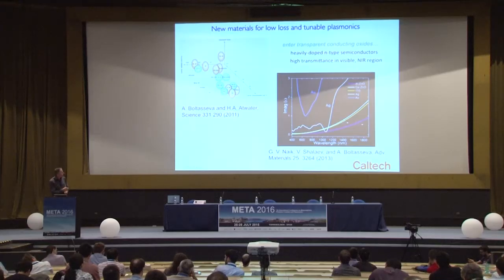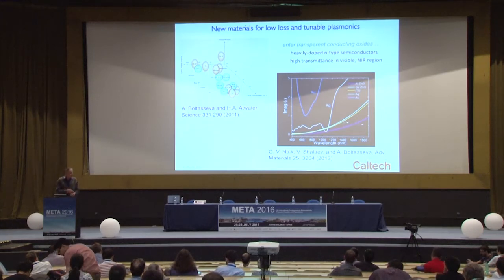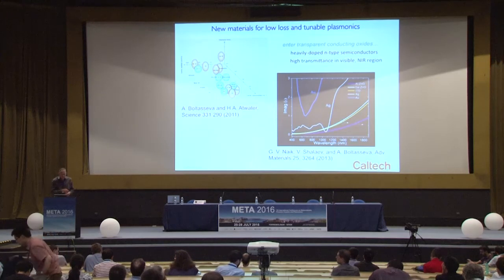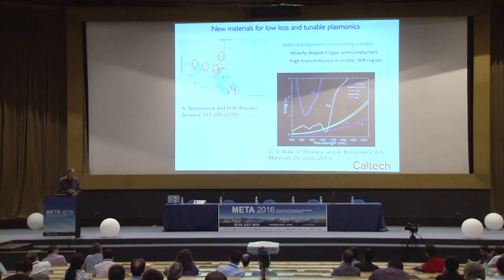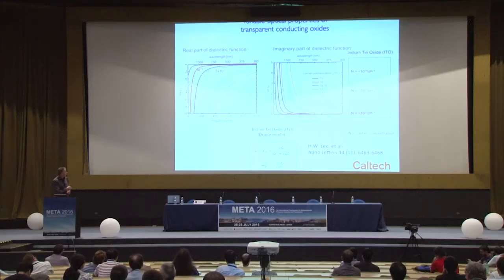But another horizon for tunable complex index materials has been to look at the properties of materials that lie between conductors and semiconductors. And this leads us to consider a broad class of materials known as transparent conducting oxides. This is an area that's been pioneered by the group of Sasha Boltasseva at Purdue University. Transparent conducting oxides, which are sitting on the laptop screens in front of you, your cell phone displays, and almost every flat display as the conductor, have carrier densities that are tunable in this very serendipitous range between 10 to the 19 and 10 to the 21 per cubic centimeter.